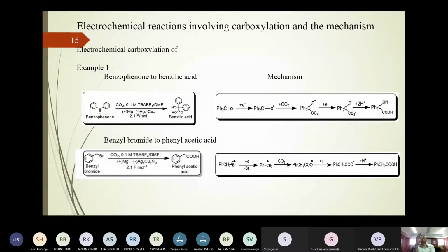So the left side shows this, the right side shows the mechanism. For example, benzophenone follows a single electron transfer, forming an anion radical, where CO2 adds to give a carboxylate anion, which undergoes a single electron transfer to give a dianion, which undergoes acid hydrolysis to form benzilic acid. The second example is benzyl bromide to phenylacetic acid, where we get phenylacetic acid. Same mechanism, except the first step involves debromination to form a radical, followed by carbon dioxide addition, followed by single electron transfer. All follow the same steps.